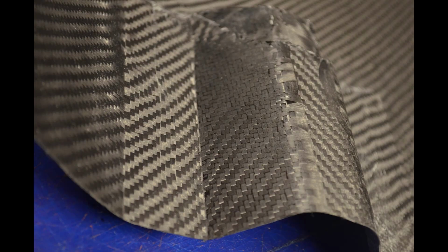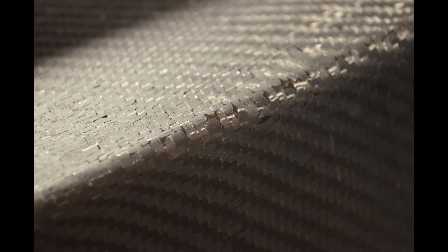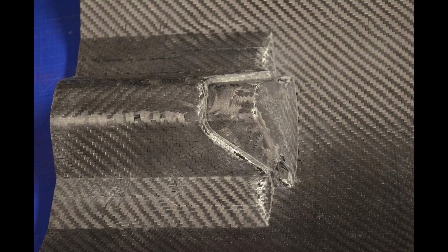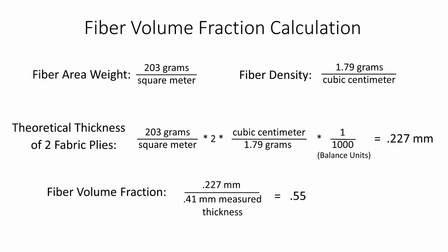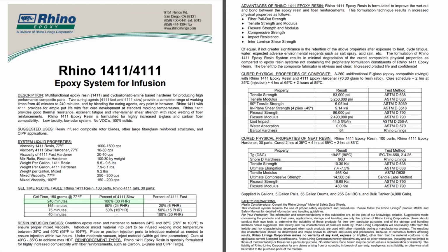After removing the part from the tool, we can see that there is significantly less bridging than the other two parts. There is generally less fiber misalignment as well. The measured fiber volume fraction is 55%, equal to the second part. One factor to consider when selecting resins with a long working life is that the time to reach a high degree of cure is also extended.